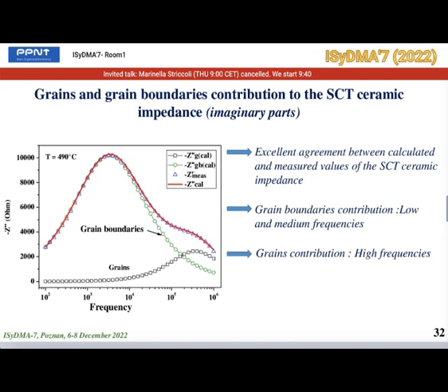We have represented here the frequency evolution of the imaginary part of the calculated complex impedance of the ceramic grains and grain boundaries, as well as the imaginary part of the measured complex impedance of the ceramic. These evolutions show a good agreement between calculated and measured values of the ceramic impedance, as well as grains contributions in low and medium frequencies, and grain boundaries contribution in high frequency.